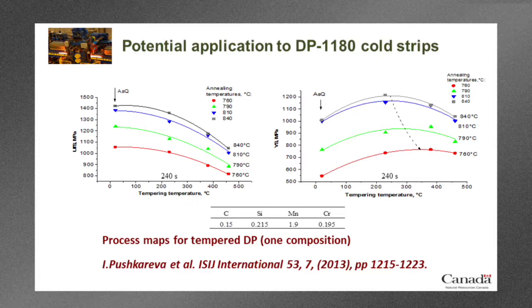Now, these steels were actually tempered, and what we would do is we temper them for 240 seconds at different tempering temperatures between, we would say, about 220 up to 470 degrees Celsius. And you can see that when you do that, the ultimate tensile strength decreases quite strongly in all cases. So this is mostly due to tempering of the martensite.